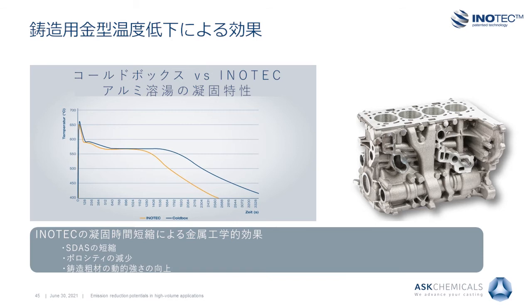An additional advantage of the inorganic binder technology INOTEC is embedded in its technological influence on the metallurgic structure of the cast aluminum parts. The metallurgic property of secondary dendritic arm spacing is mainly influenced by solidification. Thus, faster solidification leads to lower secondary dendritic arm spacing values and castings with higher mechanical strength. Lower permanent die mold temperatures in case of INOTEC already provide faster solidification. But the residual water of the inorganic binder bridge further withdraws energy from the liquid aluminum melt for evaporation, leading to an add-on effect on solidification.